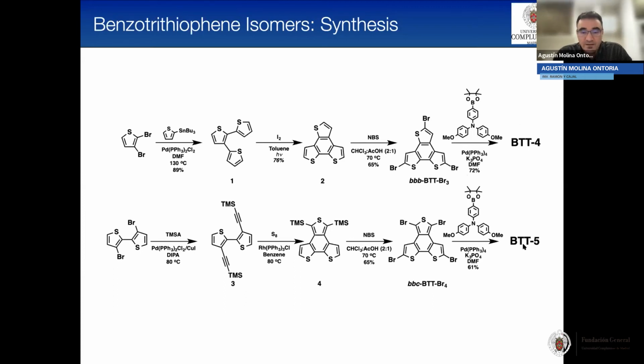For BTT5, the synthetic procedure was more challenging. We started with this dibromobithiophene. We performed a two-fold Sonogashira cross coupling. And then to form the third thiophene ring, we used sulfur in the presence of the Wilkinson catalyst, and this is the key step because the yield of this reaction was not higher than 17%, if I remember correctly. Then we brominated at the alpha positions, and finally we performed a four-fold Suzuki cross coupling.